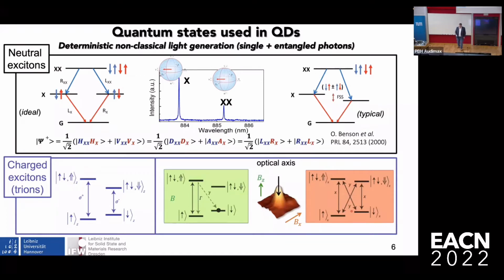You can coherently control the spins using optical pulses. And you can do this in a few tens of picoseconds. So this is very fast spin control. So let me already defend my spins in my III-V systems. Although the spin coherence times are microseconds, you can manipulate them in tens of picoseconds. So you have quite a lot of overhead. For quantum communication, you'd like them to be hundreds of microseconds, milliseconds, to give you the distance, of course. So that's the basic property.